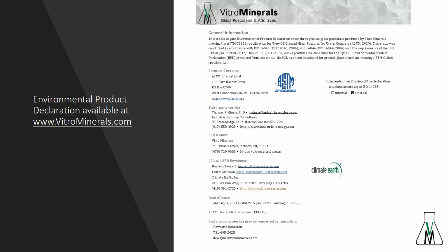Let's look at the next slide. We have an environmental product declaration that's also available on our website. In general, the embodied carbon and the global warming potential is about equal to slag cement at the same loading. So if you load 25% glass pozzolan into your mix, you get about the same carbon savings as you would with slag. Fly ash, as noted in an earlier presentation, is a bit lower because fly ash doesn't have to be ground. You almost harvest it from the power plant where it occurs, maybe particle classify it, so it's a little bit better. All of these products are great products and are very suitable for using in cement.